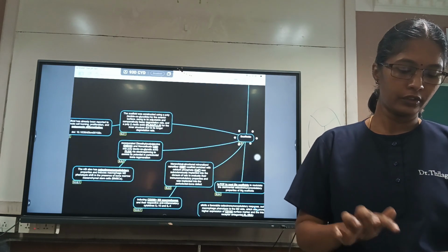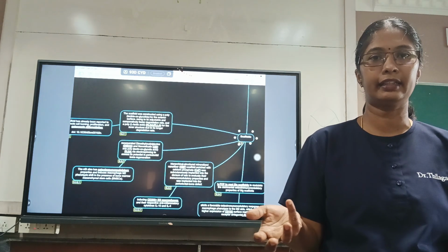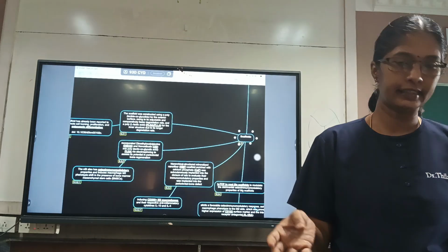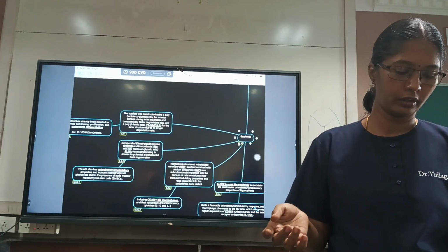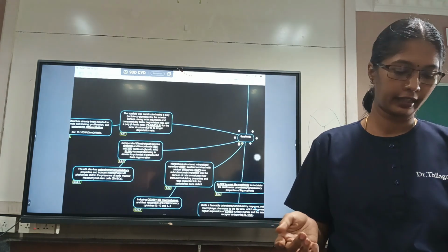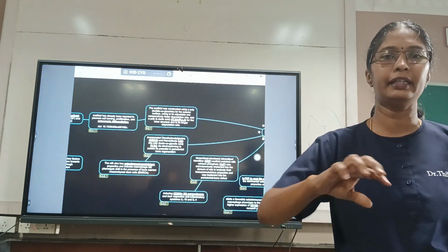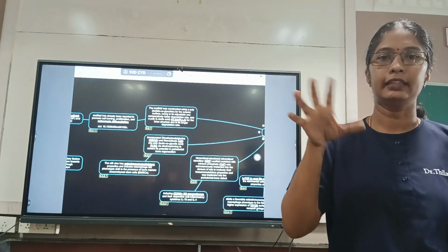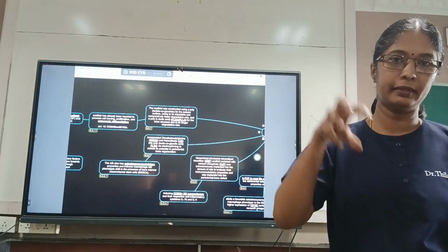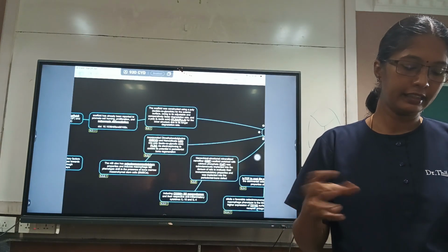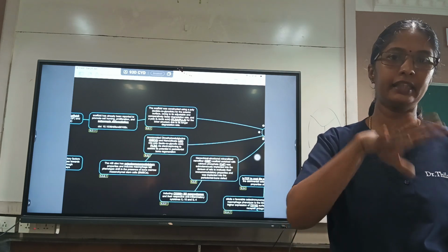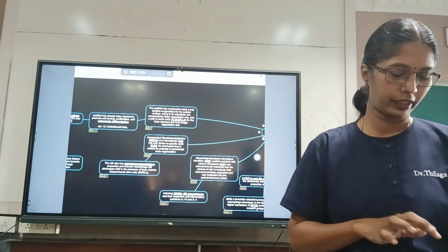And the last one is the scaffolds. So there are different kinds of scaffolds used. There are polylactide, poly-L-lactic acid, polyglycolide, lactic-co-glycolic acid. So these materials can be used to prepare a scaffold, where one material which is very hard to dissolve can be formed as an outer covering, and a core material which is easily degradable can be placed inside, so that it goes into the particular area and sits there for some time for the regeneration to happen.